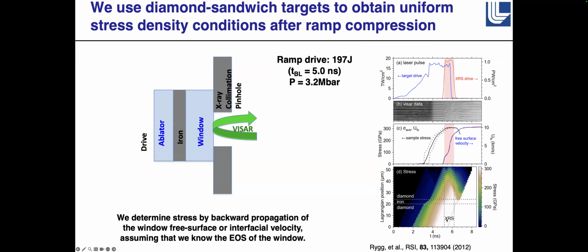And then we time the second laser that makes our X-rays so that we have this constant maximum stress. And then we can confirm that we did that correctly by measuring the VISAR data off the free surface of the diamond. And this is the timing of the laser drive and the timing of the X-ray source.